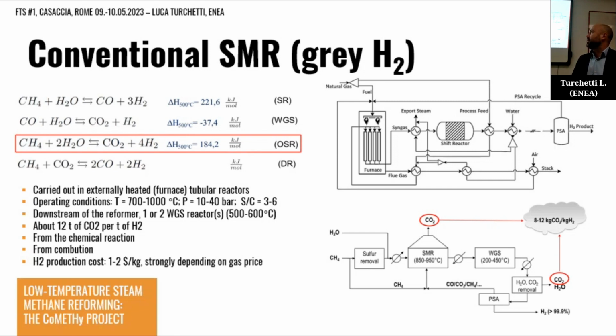Other aspects of this process: the operating conditions are between 700 and 1000 Celsius degrees. It's operated at between 10 to 40 bars. It requires steam as reactant, which is, of course, an energy-consuming element for this process. And the price today, this is the benchmark of the hydrogen production price, is between $1 and $2 per kilogram of hydrogen, but this is very strongly related to the gas prices. And we know by personal experience that these prices can be rather volatile. So this is also another issue that must be fixed.